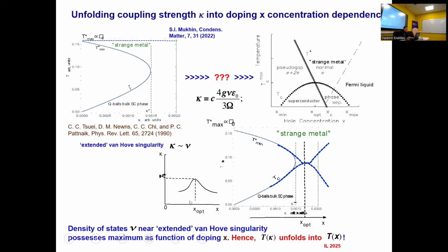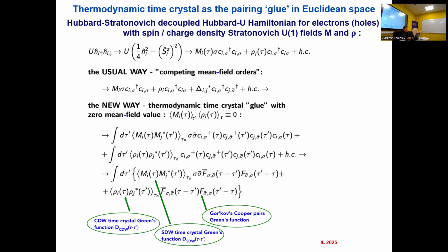So it means that when you deconvolute this plot, substituting instead of coupling strength at the nesting point with the doping dependence, you get indeed this deconvolution of this plot into two parts. And so you get this picture of the phase diagram, which looks more or less like the strange metal diagram. So the major point here is that everything that I was telling about is produced by what is called thermodynamic